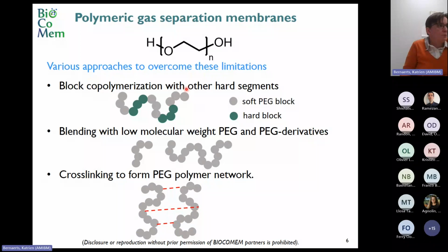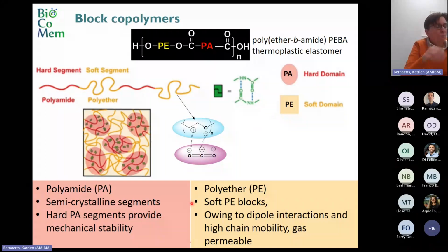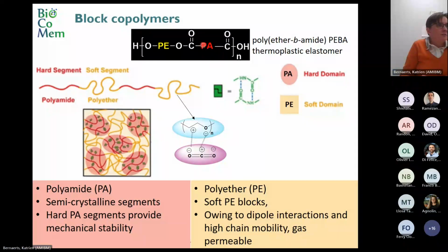One of them is to make block copolymers with other hard segments, and then the PEG is the soft segment, and you combine it with a hard segment that gives you the mechanical properties. Another way used in the literature is blending of low molecular weight PEG with other PEG derivatives, or cross-linking to form a PEG polymer network. In our project, we will focus on the block copolymer strategy, and more specifically, on block copolymers based on polyether and polyamide. They are called polyether block polyamides, or shortly PEBAs.